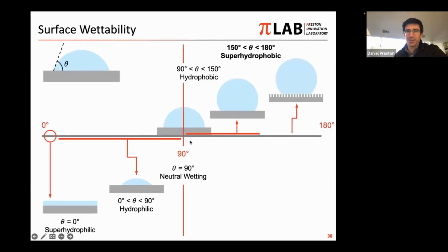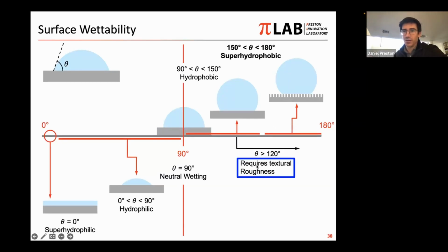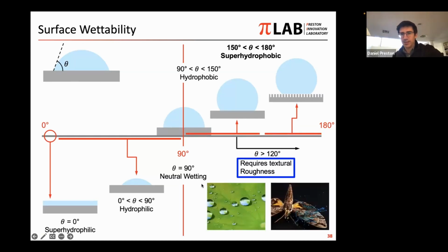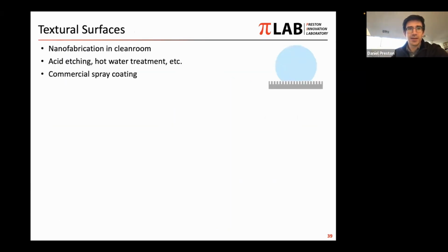And in this case, we typically design the super hydrophobic surface on the far right side of this regime map. So in this case, we can use just the chemistry to get up to a contact angle of maybe 125 or 130 degrees. But if we want to push up into the super hydrophobic, greater than 150 degrees water contact angle regime, we would require some kind of a textural roughness. And that's how things like the lotus leaf and also some insects achieve their water repellency, using both the surface chemistry and the roughness of the surface.